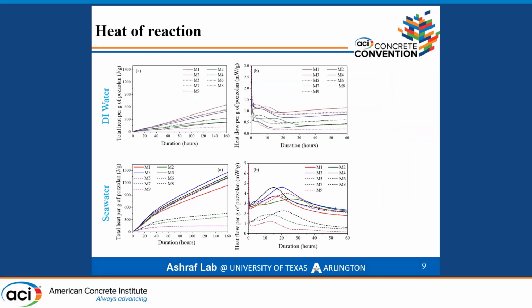The upper ones are the heat of reaction curves of the samples mixed with deionized water, and the bottom graphs are the same mixed with the seawater. As you can see, the total heat release is much higher in the seawater batches than the deionized water. The reason is that our seawater is alkaline. It has some alkaline ions like sodium and potassium, and the pH of seawater is 8.2. So this seawater acts as an activator to this calcined clay and Portlandite system. That is why the early stage reaction is much faster in the seawater batches than the DI water batches.